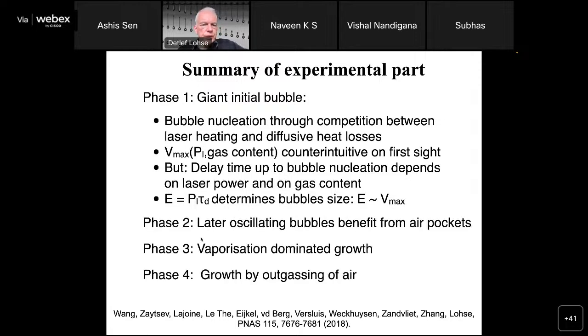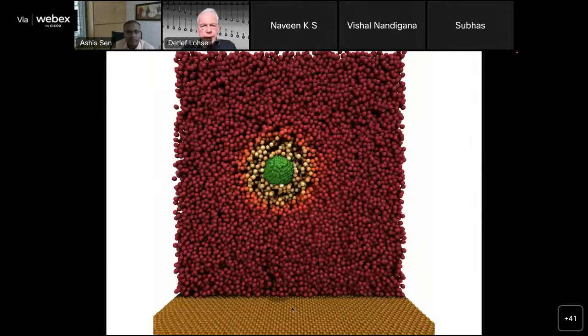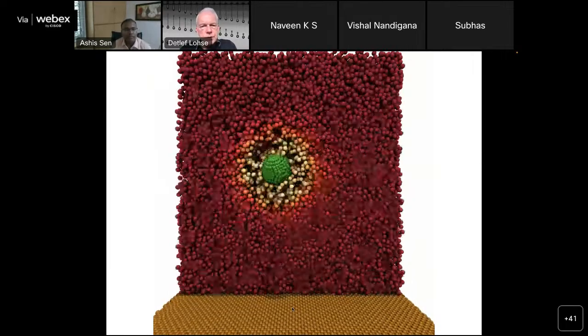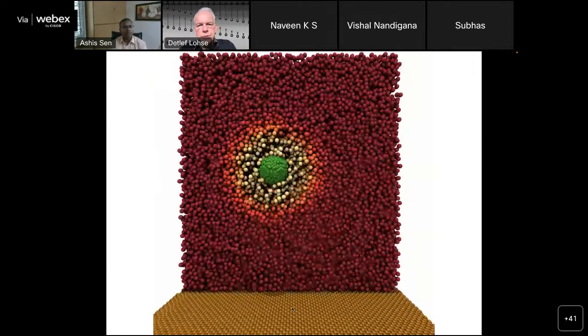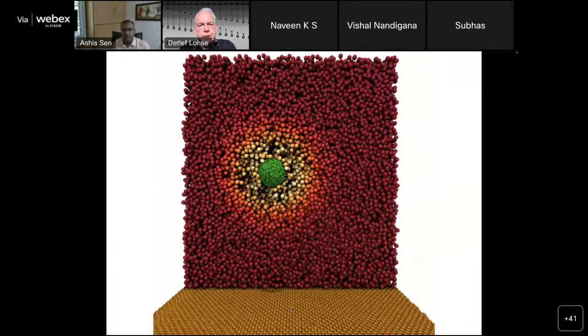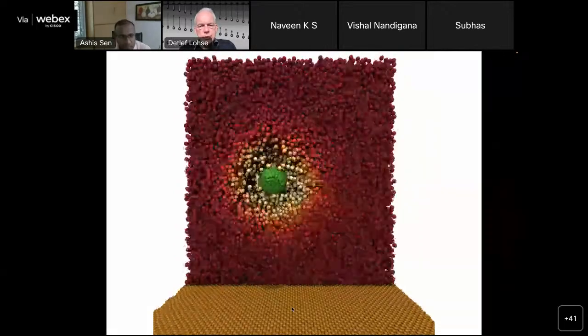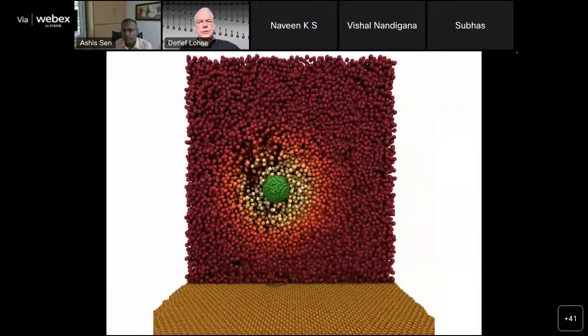This is the very early phase, and then later you have this oscillating bubble, which benefits from these air pockets. I mean, once this has happened once, of course, you have all these air pockets, and then it can happen easily later. Then you have vaporization-dominated growth, and finally growth by outgassing, which we summarize in this paper. We also did this numerically with MD simulation. I show you this simulation by Shantanu Maheshwara. I don't have time to go into this, but we redid this also with MD.